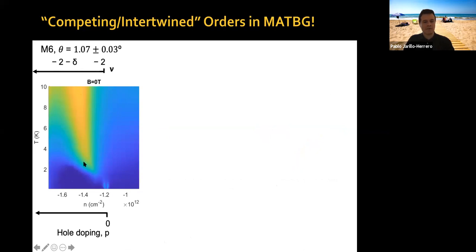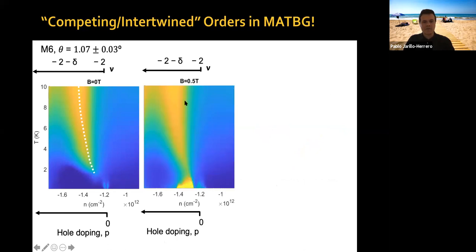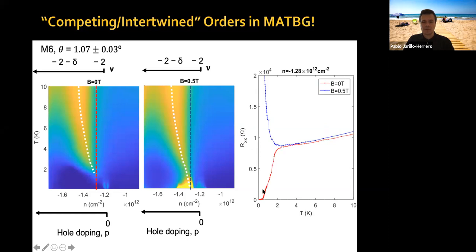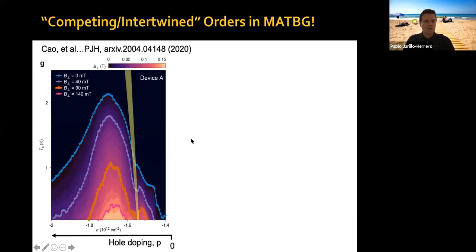resistance ridge, which happens above the superconducting dome. In this case, the correlated insulator state is very weak, barely there. And then you have this resistance ridge, there is a dent in TC. And if you go to finite magnetic field, you can see that the insulating state remains there. In fact, at nu equals minus two, it becomes a little bit stronger, but what becomes a lot stronger is this feature, coming from this resistivity maximum here. Again, if you take a trace there, you can see that at zero magnetic field this is superconducting, whereas at finite, just a small magnetic field enough to kill superconductivity, this becomes insulating. So there seems to be something which is competing with the superconducting state, and it seems to originate from this feature here.